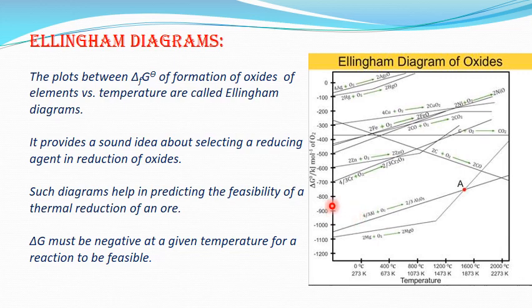My question is: out of these two values at 800 degree Celsius, which value is more negative? Minus 1000 is more negative. Delta G more negative is minus 1000. At 800 degree Celsius, delta G of formation of MgO is minus 1000, and that value is more negative. So it is very clear — a more negative delta G value means it is easier to form the oxide; the possibility of reaction is greater.